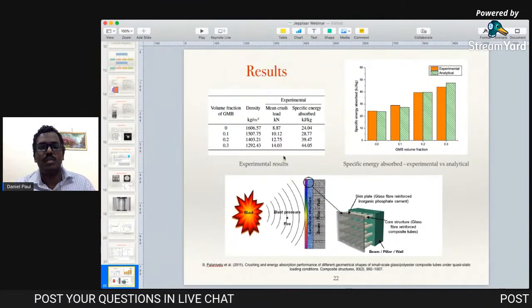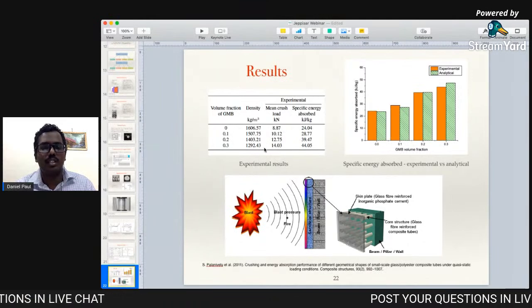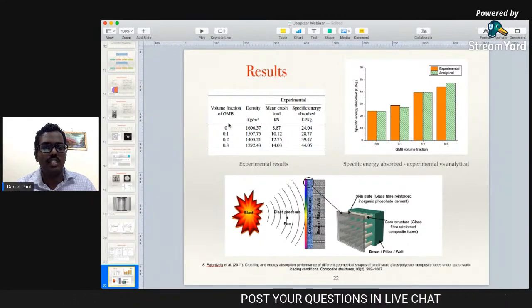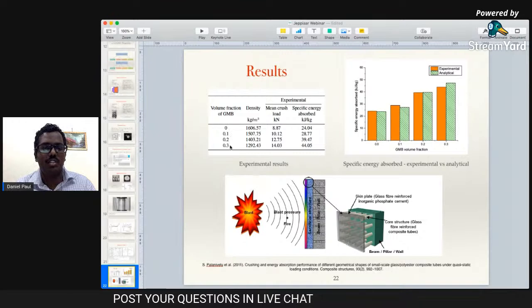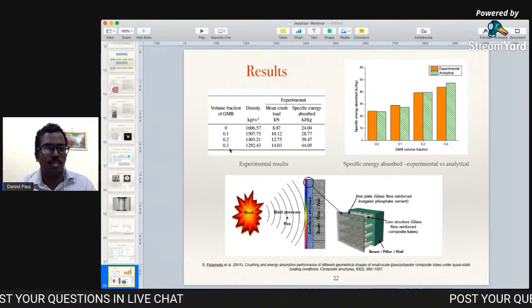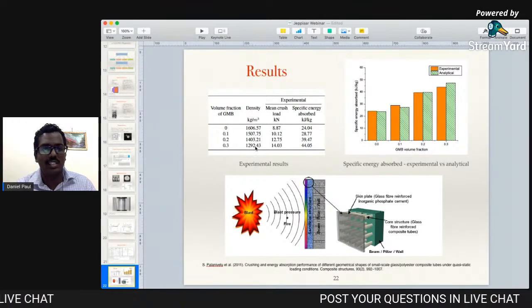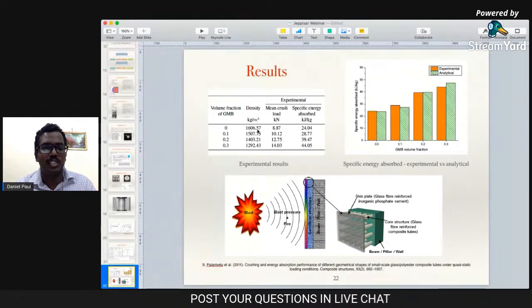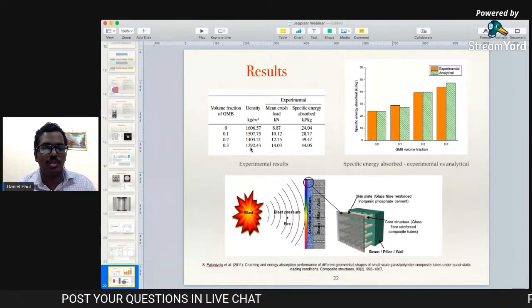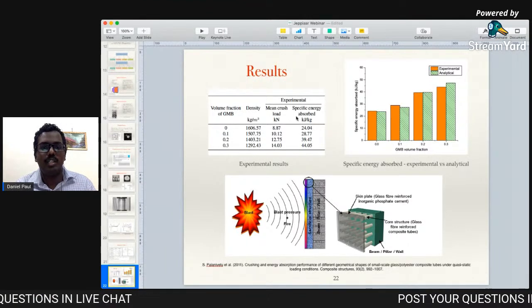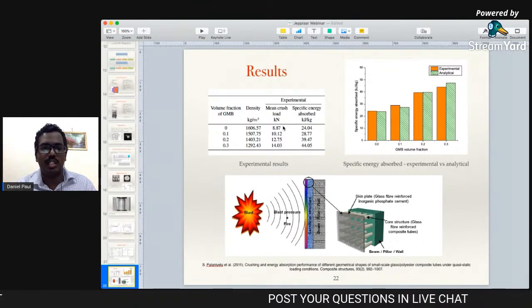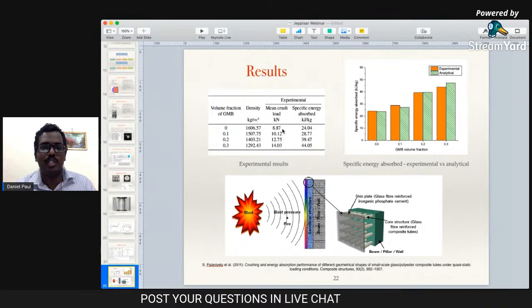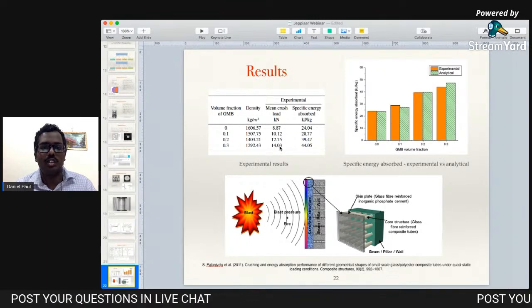This first table shows the numerics involved. As we see, when we increase the volume fraction of the glass microballoons, or the hollow particles, the density decreases rapidly from around 1.6 grams per centimeter cube to 1.2 grams per centimeter cube. The mean crush load, as we saw earlier in the graph, increases from around 8.87 kilonewton to 14 kilonewton.